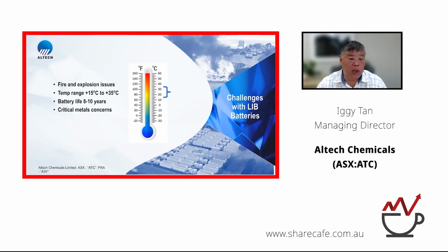In a lithium-ion battery, there is a volatile liquid electrolyte, and that also contributes to the fire and explosion risk. The battery life of a lithium battery is generally 8 to 10 years, and that's also because the lithium degrades every time you charge and discharge the battery, also relating to the liquid electrolyte. And then the final concerns are the critical metal concerns.